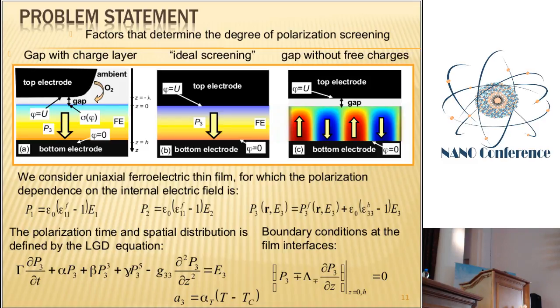The electrostatic equations are primitive. It is the Laplace equation outside the ferroelectric and the Poisson equation with inhomogeneous polarization divergence inside it. The only thing I would like you to pay attention to is that in the boundary condition on the film surface, we have the density of the 2D screening charge on this surface.